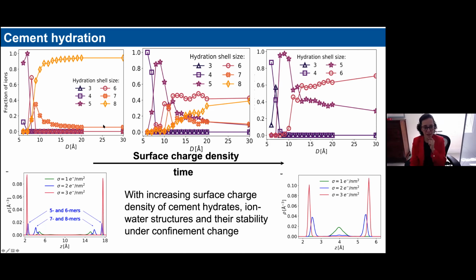Why? Because during cement hydration, as I was saying, the surface charge of the nanoparticles actually increases over time. This is a very important characteristic of the development of the cohesion in this material. And so you can see that in our calculation, we can distinguish what happens at early times, where you have relatively lower surface charge. With relatively lower surface charge, the ions are less squeezed close to the surface. So at relatively large confinement, you can still accommodate full hydration shells, very similar to those in the bulk, at relatively large separation of the two surfaces.